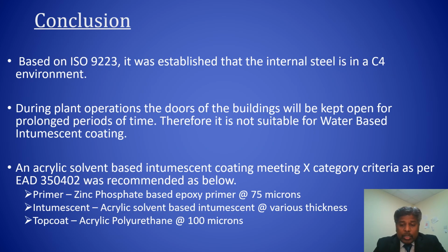Based on the theoretical calculations and the practical tests that were done on this coating system, which includes the zinc phosphate primer, the solvent-based intumescent and the PU top coat, we can see that for the internal steel located in a C4 environment, the solvent-based intumescent provided and will provide adequate protection from fire and corrosion. As we know, during plant operation, the expectation of the asset owner is that the door will be open. Therefore, a coating system which is approved for X category as per EAD 350402 shall be used, and a water-based acrylic intumescent shall not be used.